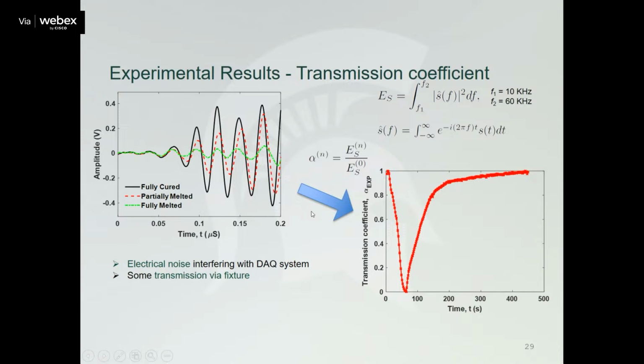If you look at the transmission coefficient, this is a very interesting result. You control the temperature over time because of the feedback loop, so you can see the transmission coefficient dropped significantly when you go to high temperature over time, then it goes back. This is the cooling stage. What does this mean? It means this can work as a reversible adhesive, right? You melt it, you have less energy transmitted, they detach and dismantle, then you bond this again if you cool this down.